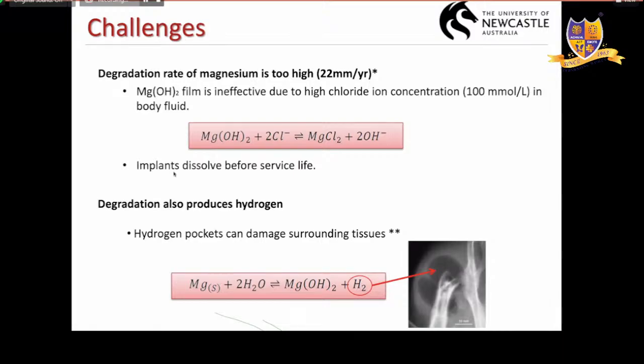The second problem, which is associated with the first problem, is because of the high degradation rate, they produce a lot of hydrogen, right? As I said, it's an electrochemical reaction. Magnesium dissolves and hydrogen evolution happens. So the more the magnesium dissolving, the higher the hydrogen. So these small hydrogen bubbles coalesce, they come together and form a big pocket near the implant. When you have such a pocket of gas, it is difficult for the bone to heal. There's no contact between the body fluid and the implant and bone. So bone healing is delayed by that process.